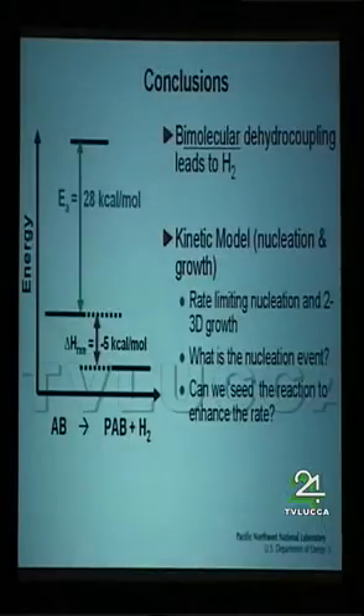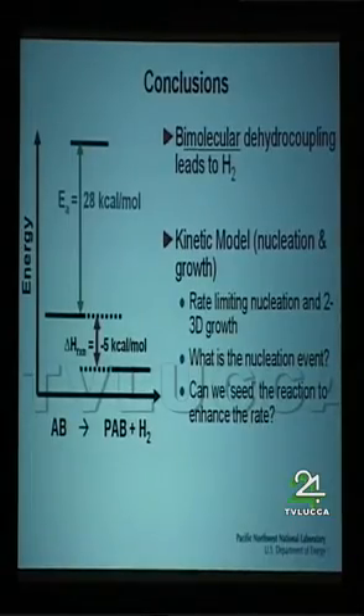So the conclusion is summarized best, I think, with an energy level diagram here. We've got an activation barrier of 28 kcal for the rate limiting step, starting with pristine material. And the heat of reaction is 5 kcal per mole exothermic. That's the other interesting thing about this compared with carbon systems, which are endothermic for release of hydrogen. This thing is exothermic with release of hydrogen.